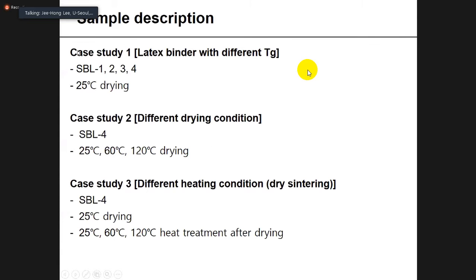So, summarizing the samples, the first case study is latex binder with different Tg. All coating layers were dried at 25 degrees and different Tg latexes were used. In the second case, the highest Tg latex was used and the drying temperature was different. In the third case, also the highest Tg latex was used for the coating layer, and it was dried at 25 degrees Celsius. And after drying, the coating layers were treated with heat at 25, 60 and 120 degrees Celsius.